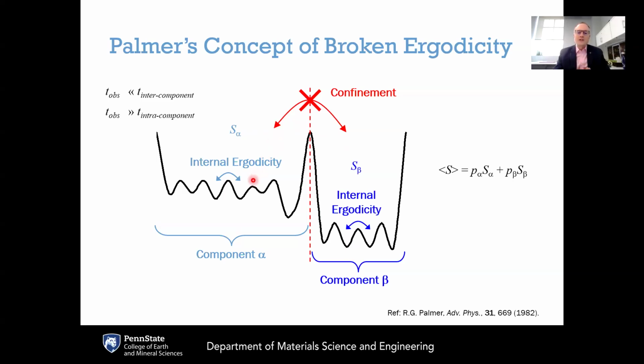Now, Palmer's notion of broken ergodicity has two main assumptions. The first is internal ergodicity. And internal ergodicity means that if we define an observation timescale, t observed, that observation timescale is much longer compared to the timescale for transitions between microstates within the component. In other words, we're giving the system plenty of time to have a local equilibration within the component such that within the component, ergodicity is satisfied. That is the condition of internal ergodicity.